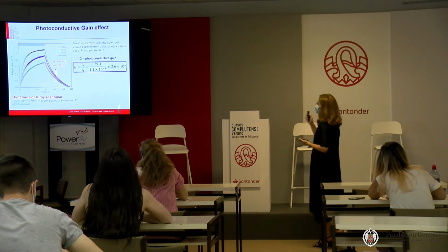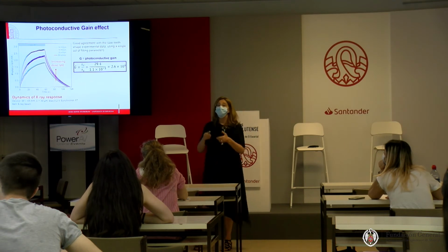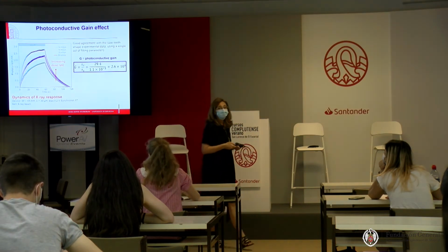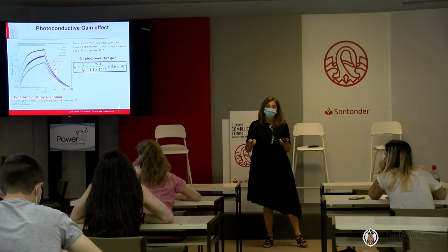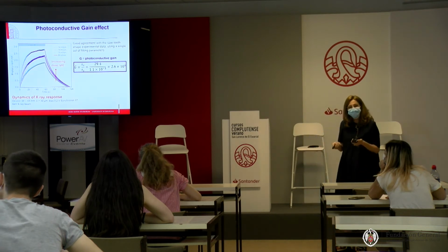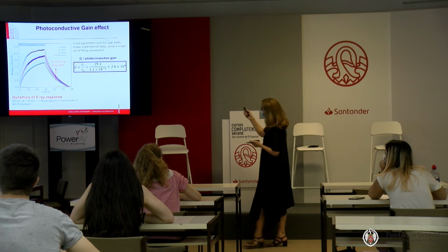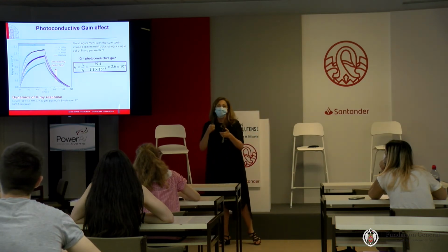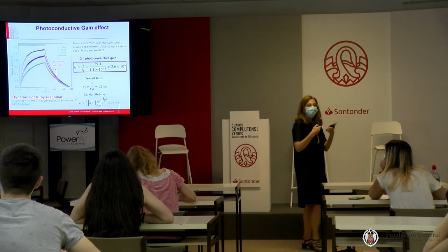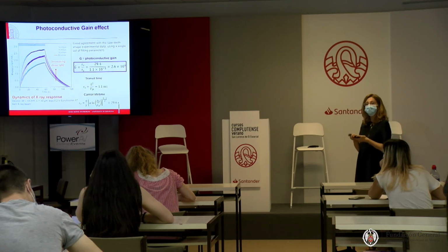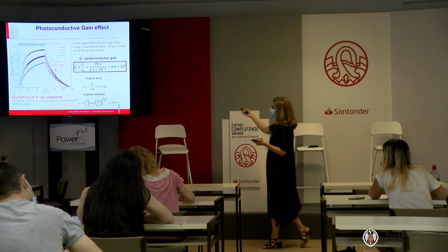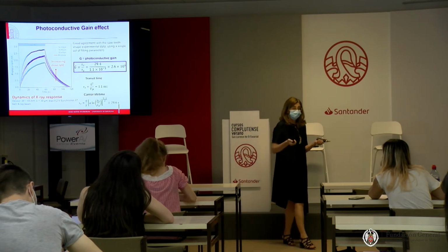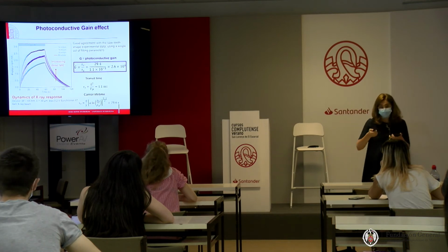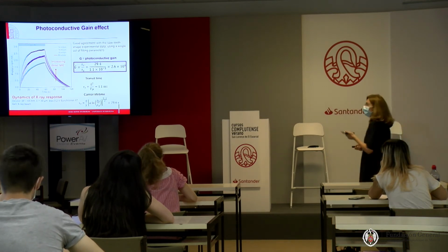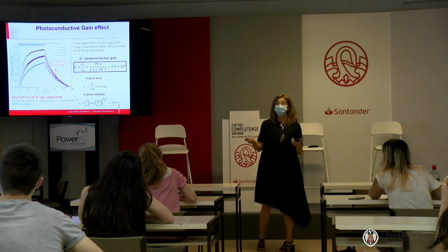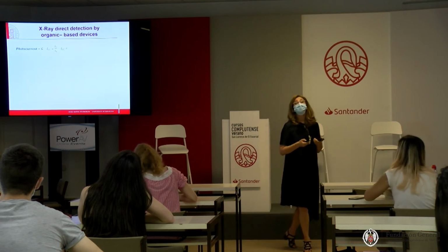So this photoconductive gain is the key point that we need to study in order to control and enhance the X-ray detection from our materials. The photoconductive gain is present also in other materials under visible lights, but under X-rays was a bit of a novelty. And it is interesting because the photoconductive gain is based on two parameters, the transit time and the carrier recombination lifetime. If we control either the geometry of the device and control the transit time, or the defects in the material and therefore the carrier recombination time, we can modify the gain. And if we modify the gain, we modify the collected photocurrent, which is our output that we want to maximize.